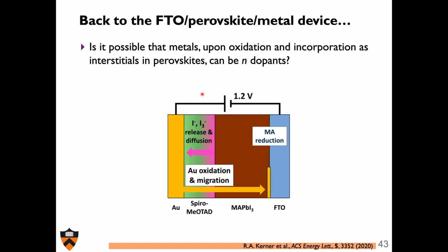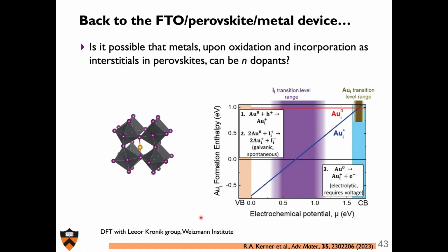So we went back to this device, and we thought more about metal infiltration. And we wanted to see if every time a metal cation enters this lattice, do I actually n-dope it? Is that the other side of the redox equation? We got the aid of Leeor Kronik at the Weizmann Institute in Israel. They did some density functional theory on a gold interstitial. And what they found was that the gold interstitial transition level sits somewhere in the conduction band, in other words, right at the edge. In other words, if you do have a gold plus interstitial, it should come along for the ride with an electron. That should be the kind of stable state of a gold plus interstitial.